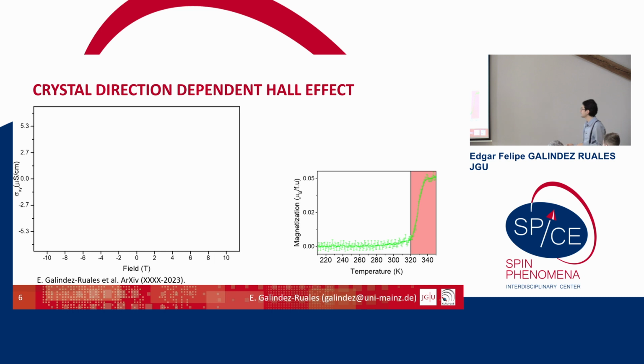Then we say, okay, let's pattern some Hall bars and see if we can observe some anomalous Hall effect arising from this antiferromagnet that is not quite an antiferromagnet, so it can have Hall effect. We observe at really low temperature some increase, and this value for the increase is also consistent with the spin reorientation on the hematite. Because if you pass from the easy axis phase to the easy plane phase, you will have some magnetic moment, and then you can have anomalous Hall effect.